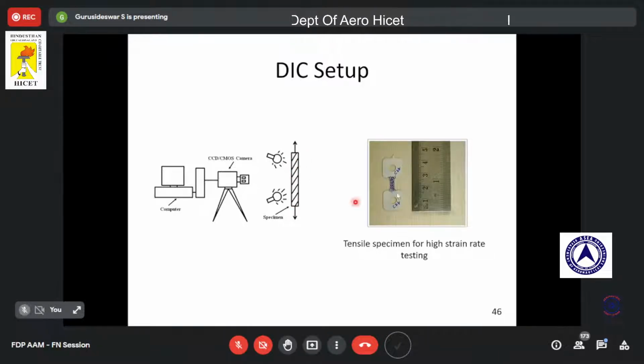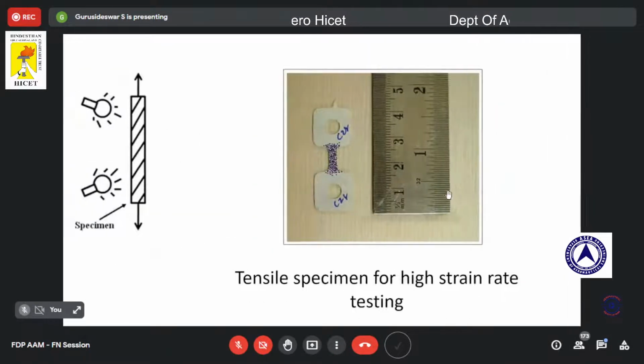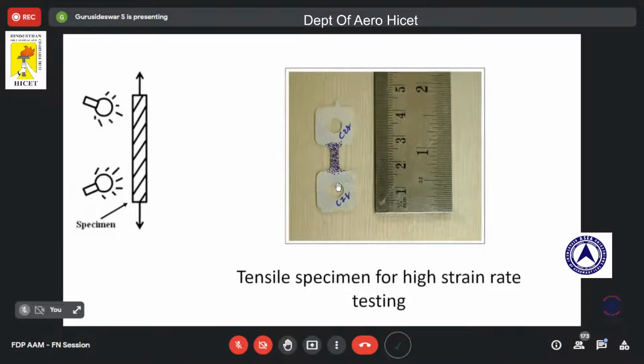So this is the sample which we have used for this high strain rate testing. Based on the literature survey, we have chosen this sample. It is a 3 mm width and 10 mm gauge length, and here we have taken the speckle pattern. So this is a speckle pattern.